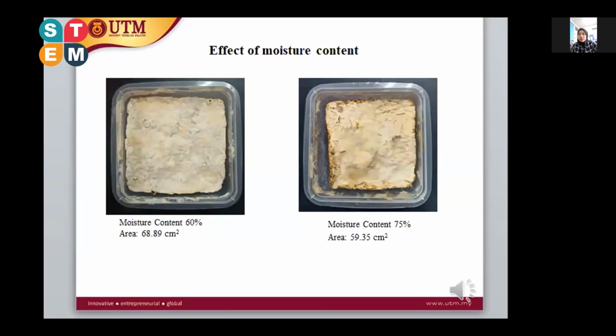Next. So this one is the effect of moisture content, and it shows a different area with a different moisture content, where the moisture content of 60% shows the biggest area, which is less shrinkage than the moisture content at 75%.